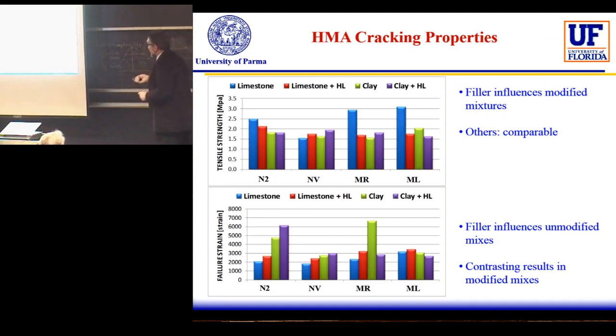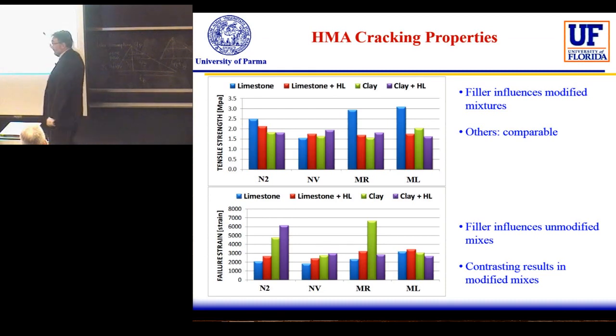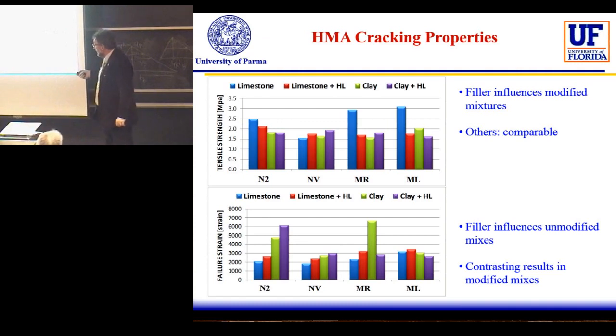The first series of results was in terms of tensile strength, and we started to see some differences, but we see that filler influences the modified mixtures more. So where the polymer is, we have differences, but when we have no polymer, we have less difference as a function of the different filler applied. In terms of failure strain, we saw that filler influences modified mixtures, while for unmodified mixtures we have contrasting results. We are not able to clearly identify a path in the behavior of the material.